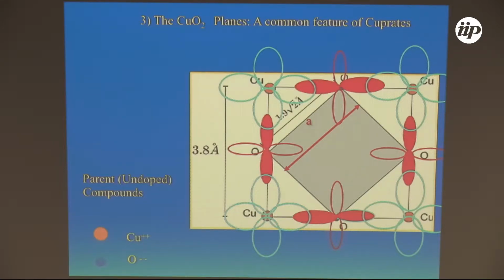Now, this is well known, but from the point of view of the oxygen lattice, an attentive analysis shows the following. If you take, for example, the px orbital and the py orbital in the nearest neighbor, they are bridged by overlapping with the copper orbital, whereas the py here and the px here are not.